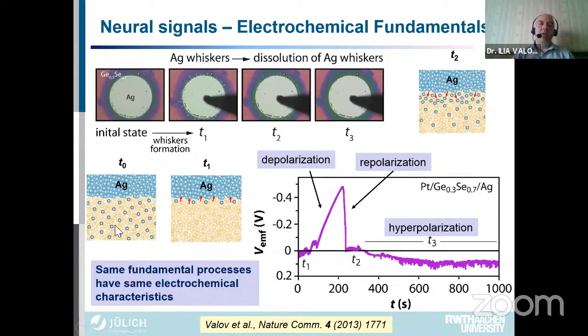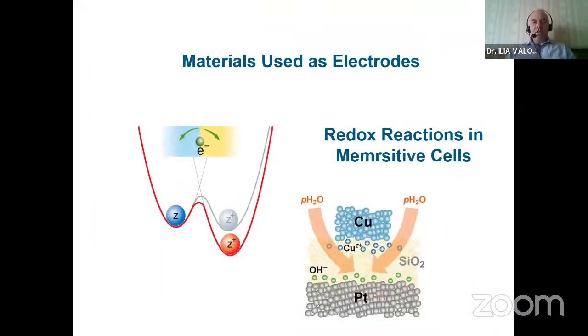And so in fact, what happens here is that we start again to dissolve silver within the electrolyte. The reason that we have the same fundament here is again the diffusion equation, which is responsible for the behavior of the cell. So initially you change this equilibrium situation, you extract ions, then they are coming back, and for this reason you see also this type of time distribution, the potential time distribution in the artificial cell. So this is the reason we are using memristive devices for neuromorphic computing, because they emulate very well, based on the same principle, the operation way of the biological neurons.